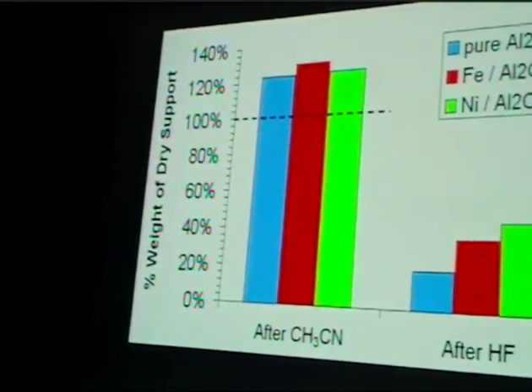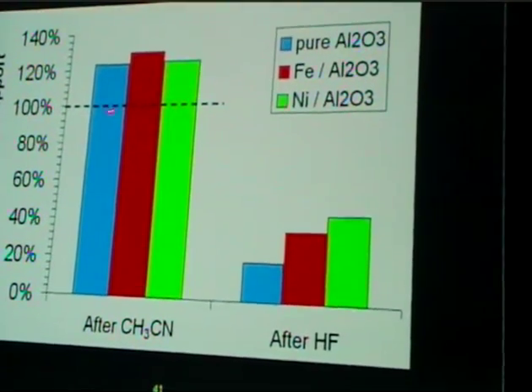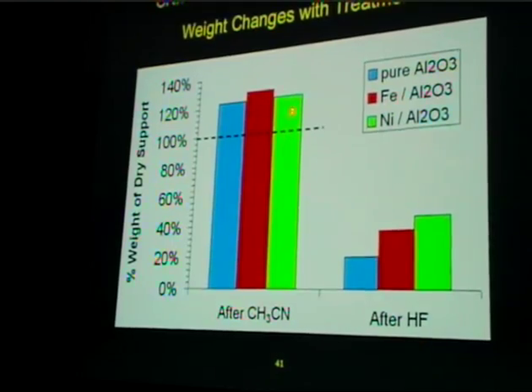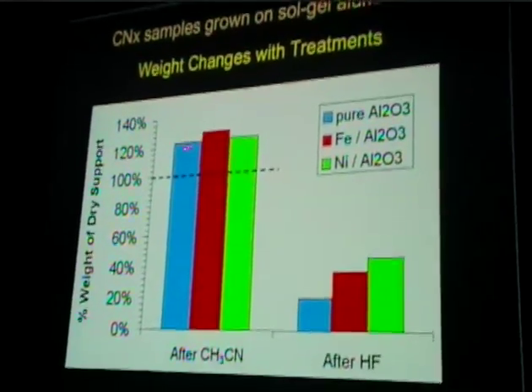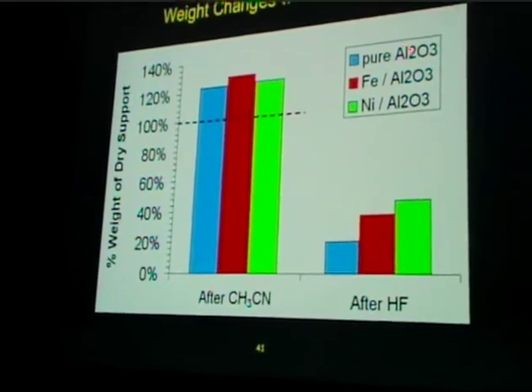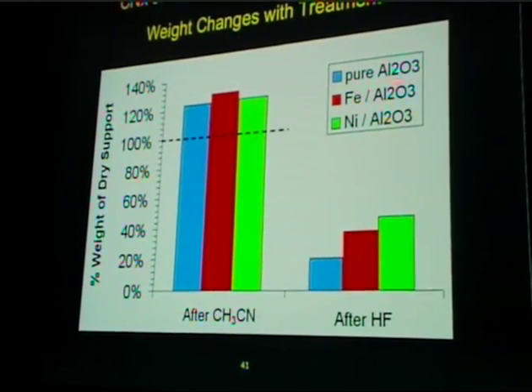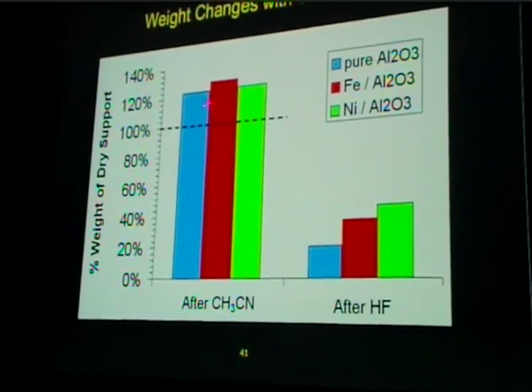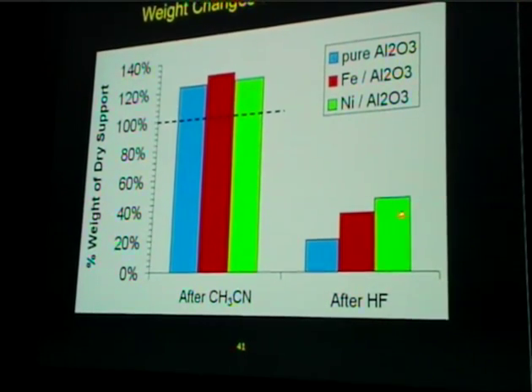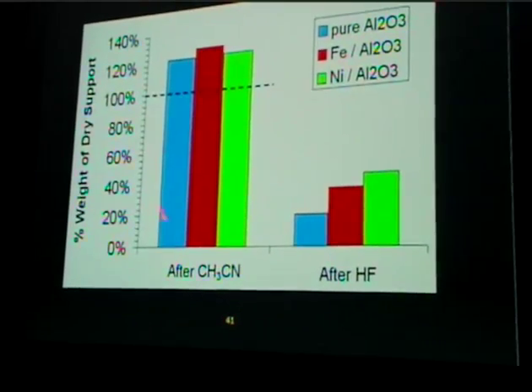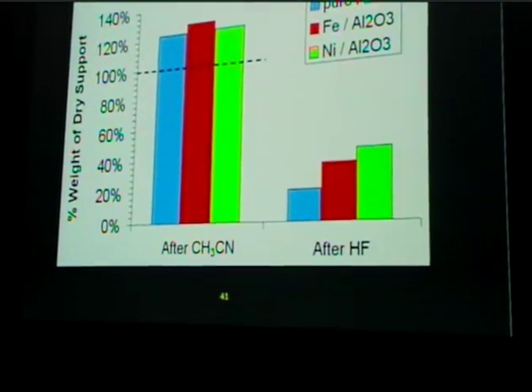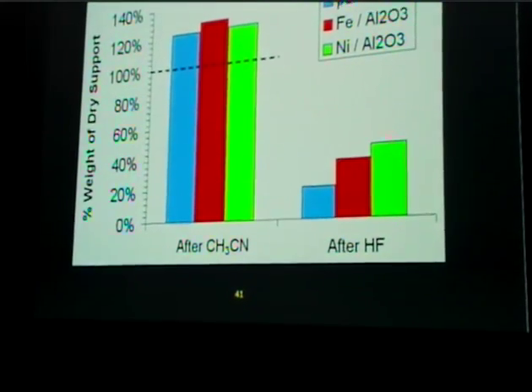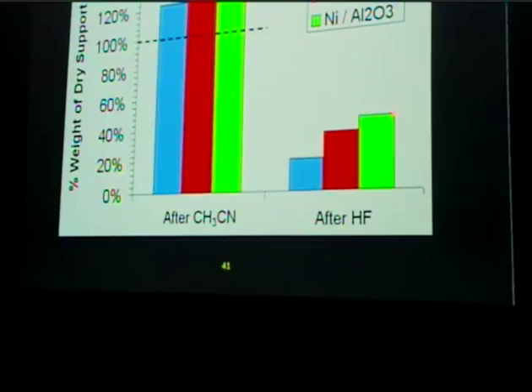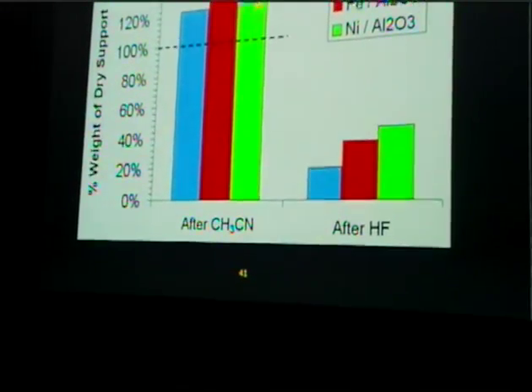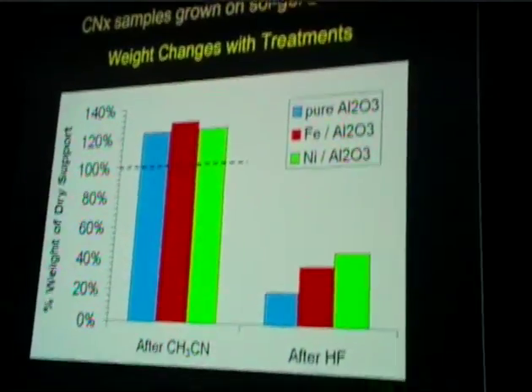First of all, if we look at the weight gain over these alumina supports, here is the weight of the alumina support, and this is the carbon deposited. So we have close to 20–30% carbon depositing, and these are different support materials with iron, nickel, or without. And after hydrofluoric acid washing, we're essentially losing pretty much all of the alumina. But again, especially for example, if you look at nickel, there's probably some of the metal still left behind, because this clearly is more than the green bar, which is due to the deposition of carbon here.